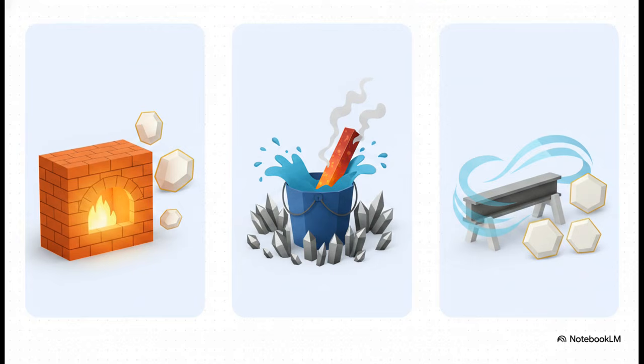But here's the catch. The speed of that cooling process changes absolutely everything. You can think of cooling rates as a sort of Goldilocks scenario. If you cool the steel very slowly in a furnace, a process we call annealing, the carbon atoms have plenty of time to shuffle around and form large crystals. That gives you a softer, highly ductile steel. On the totally opposite end, if you cool it violently fast by quenching it in cold water, you trap the carbon right in place. That forms martensite. It's an immensely hard but very brittle structure, which is honestly terrible for welding. But if you cool it just right, simply out in the air, you get normalized steel. That's the perfect fine-grained balance of strength and ductility we need for construction.